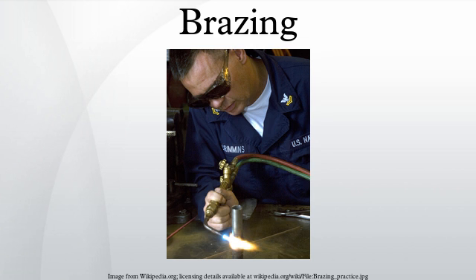Braze alloy is generally available as rod, ribbon, powder, paste, cream, wire and pre-forms. Depending on the application, the filler material can be pre-placed at the desired location or applied during the heating cycle. For manual brazing, wire and rod forms are generally used as they are the easiest to apply while heating. In the case of furnace brazing, alloy is usually placed beforehand since the process is usually highly automated.